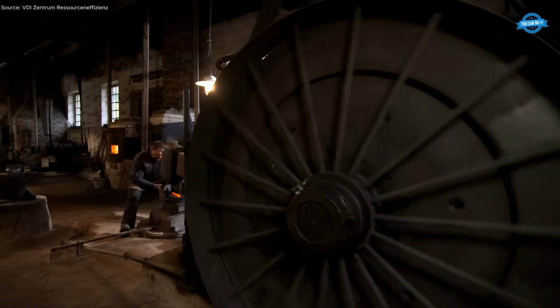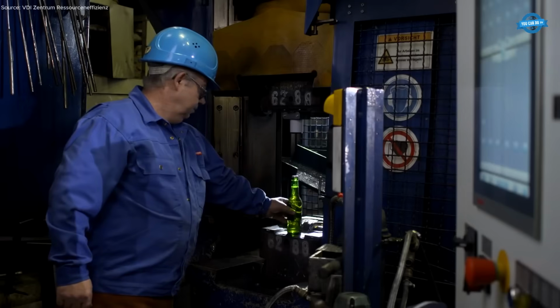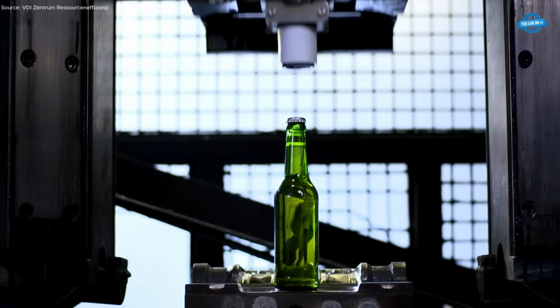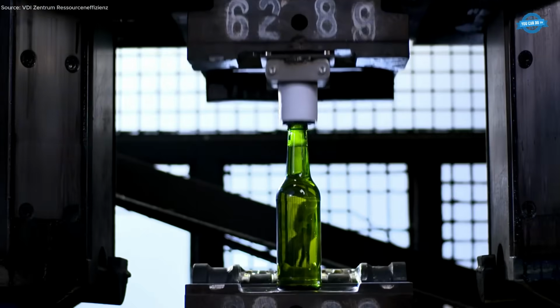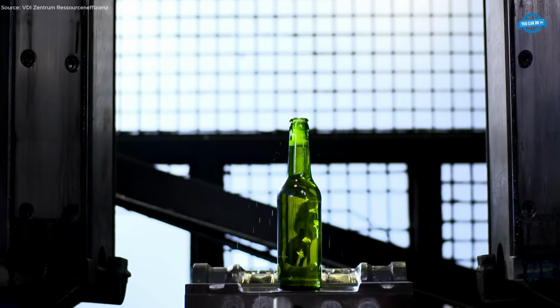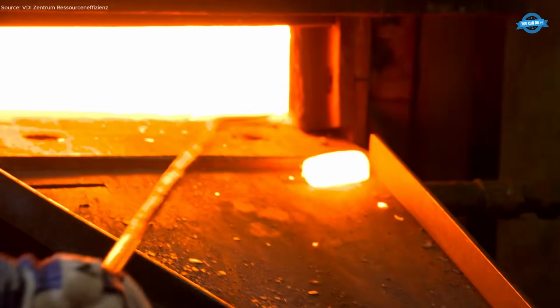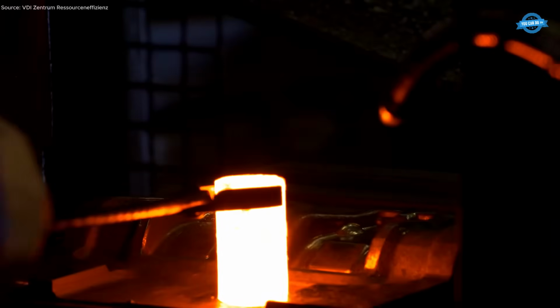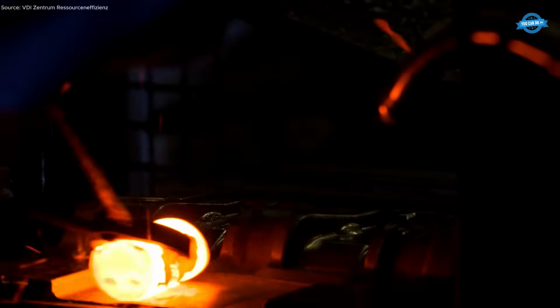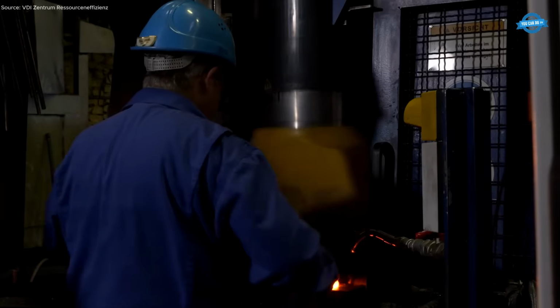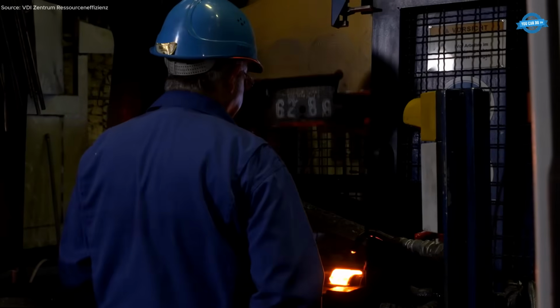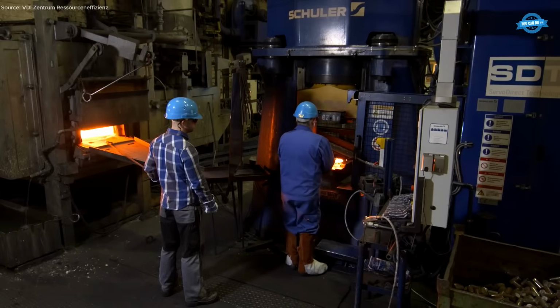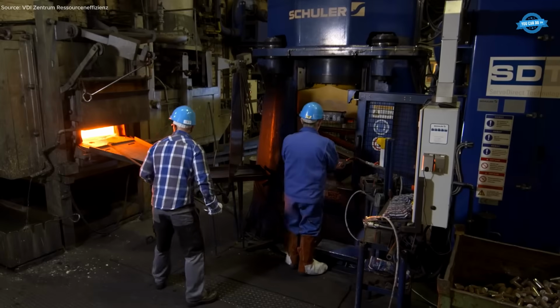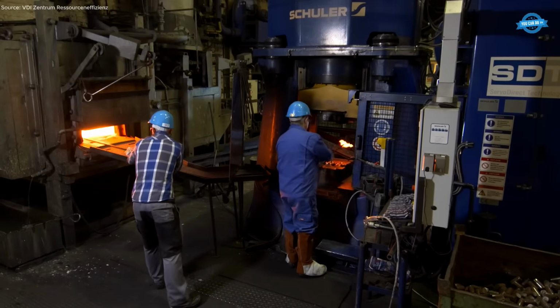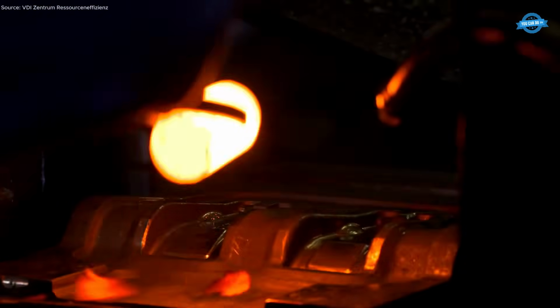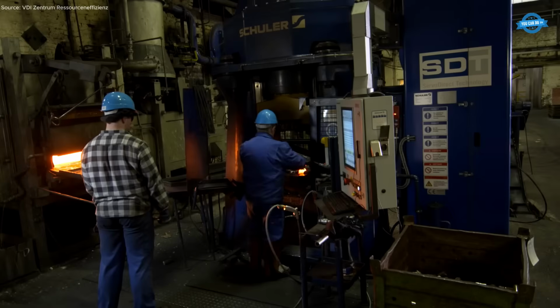At Schuler GmbH in Hagen, Germany, the linear hammer operates alongside a 19th-century double-belt hammer. While the old system strikes red-hot blanks at more than 1,000 degrees Celsius with a blow energy of 6 meter-tons, the new hammer can stop within 0.05 millimeters, producing highly accurate parts. Despite striking with the force of a 1-ton drop from 2 meters, it applies this energy only until the desired shape is achieved. This saves wear on the dies and reduces wasted energy.